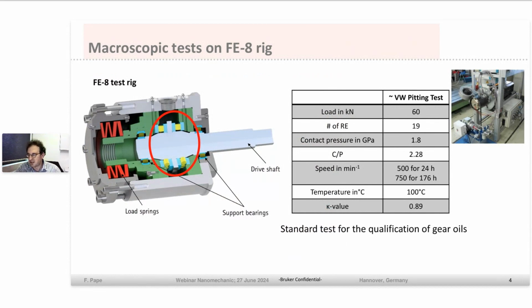High load is applied with disc springs and axial load, and these bearings run under harsh conditions, under high load, under increased rotational speeds. For the first 500 RPM is for 1 day, like a run-in, and after that for 176 hours under 750 RPM. And the temperature, we investigated the bearings up to 100 degrees Celsius. And to qualify the oils with additive packages, these bearings have to stand this 200-hour test.